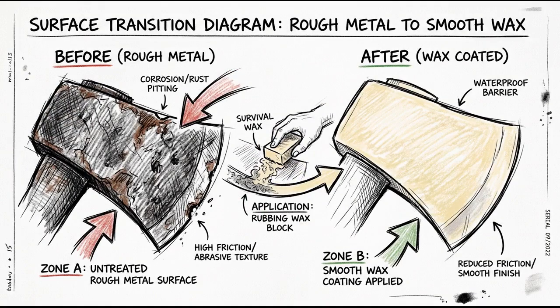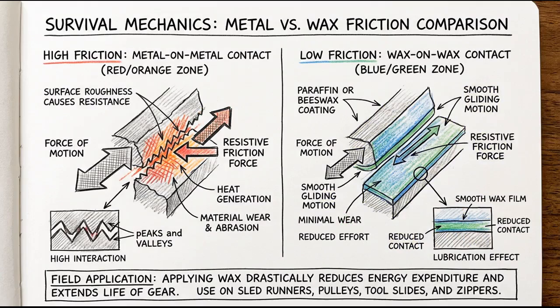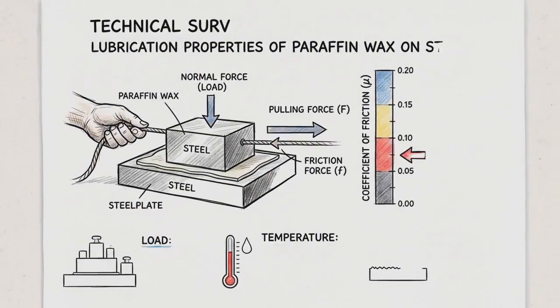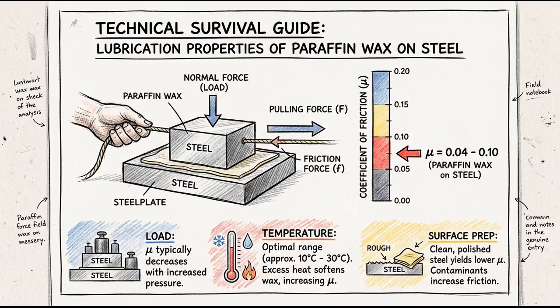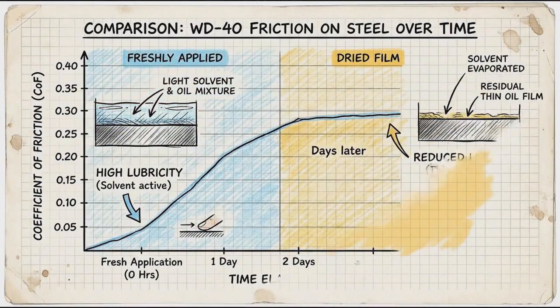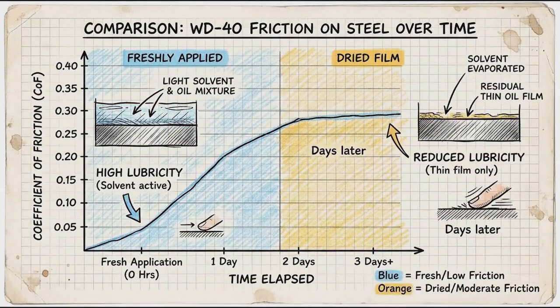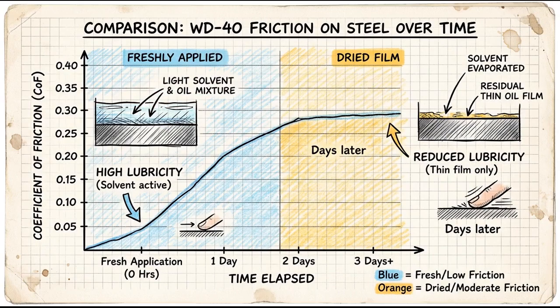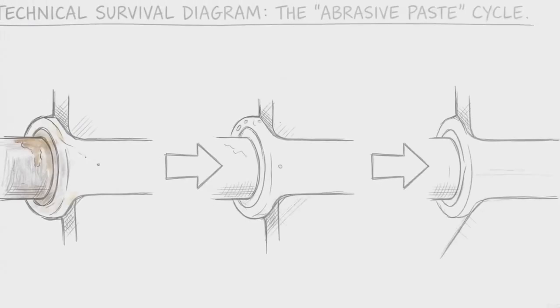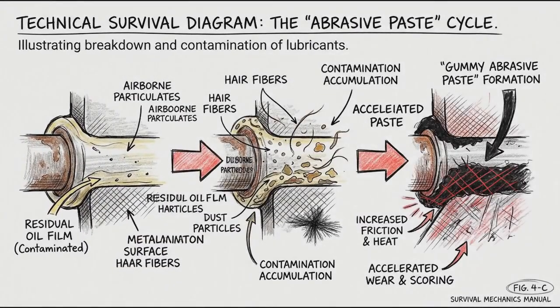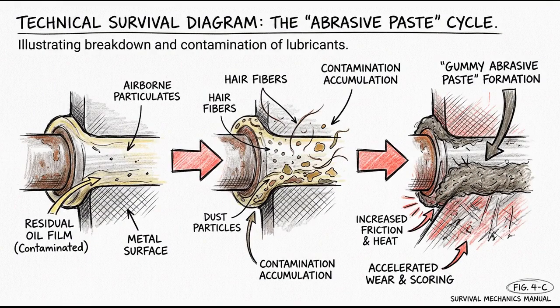Wax-on-wax contact has dramatically lower friction than metal-on-metal contact. The coefficient of friction of paraffin wax on steel is 0.04 to 0.10, depending on load, temperature, and surface preparation. For comparison, WD-40 on steel starts at about 0.05 when freshly applied, but rises to 0.20 to 0.30 within days as the solvent evaporates and only a thin residual oil film remains. That residual oil film then collects dust, hair, and airborne particulates, forming a gummy abrasive paste that actually accelerates wear. Paraffin wax does not evaporate at room temperature.